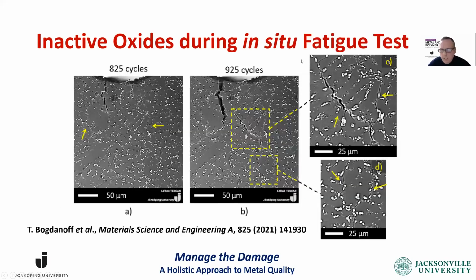And this is a study by some of my colleagues here at Jönköping, in situ fatigue test. What they noticed is that there were these cracks that appeared in the most unexpected places, on the tensile side. These cracks, which are not fatigue cracks, these are just oxides opening up. This is the damage presenting itself in a tensile stress state.